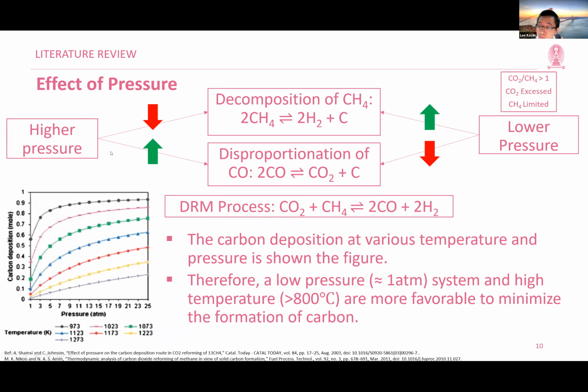So for the effect of pressure, we split it into higher pressure and lower pressure. If you look at the figure on the left, if you pick a line which is a constant temperature, as the pressure increases from 1 to 25 atmospheres, the carbon deposition increases as well. The reason for this is if we are taking the feed ratio more than 1, methane will be limited, so the first equation we don't really need to focus on. Higher pressure in the literature shows that it encourages the disproportionation of carbon monoxide. Lower pressure discourages it.